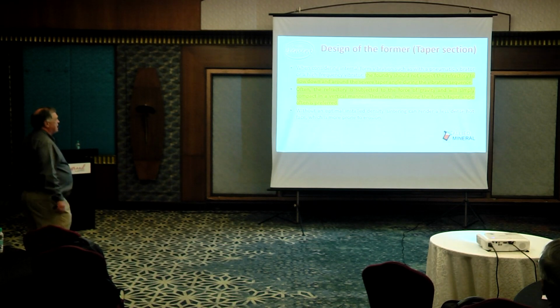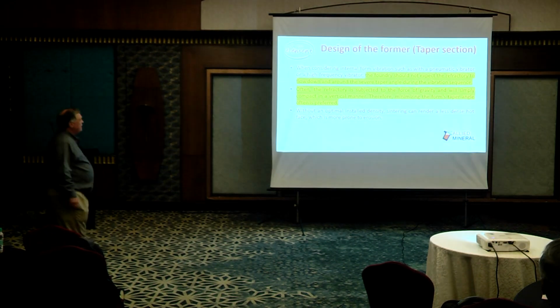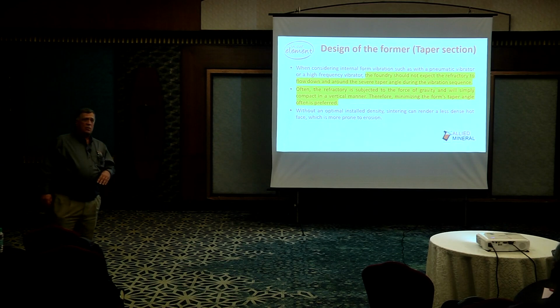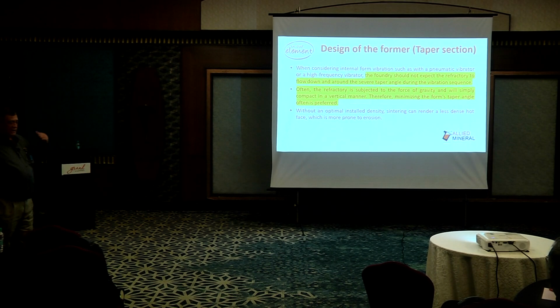Taper section, the foundry should not expect the refractory to flow down and around. This is what I was talking about earlier. I would reduce the thickness of the layers when you get into the taper section, depending on the severity of the taper, because you really have to try to get in there. And if you're using a jolter, then you want to slow the rate of ascension so that you're getting more vibration in the taper than you do in the sidewalls. All of that is normal so that you can get maximum density.